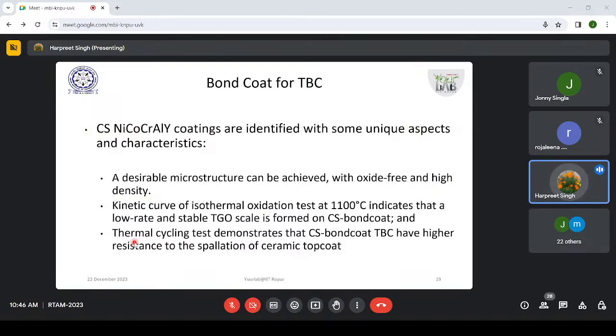Bond coats for TBCs. This is something of interest to the aerospace industry. Those who are aware of thermal barrier coatings know that usually thermal barrier coatings are provided on turbine blades, but the problem with them is that TBCs are mostly ceramic, and then we have the substrate which is some alloy, and there is a lot of CTE mismatch. What is CTE? It's the coefficient of thermal expansion. That mismatch is compensated with the help of these bond coats. But the bond coats produce their own challenges in terms of their oxidation and so on.